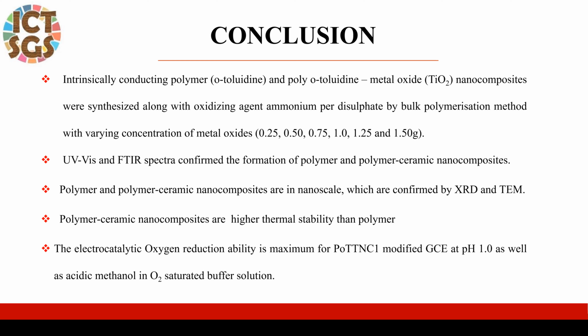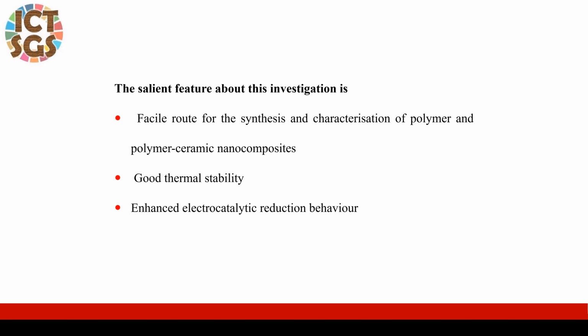The electrocatalytic oxygen reduction ability is maximum for PoTTNC1 modified GCE at pH 1 as well as in acidic methanol in oxygen saturated buffer solution. The salient features of this investigation are facile routes for the synthesis and characterization of polymer and polymer ceramic nanocomposites, good thermal stability, and enhanced electrocatalytic reduction behavior.